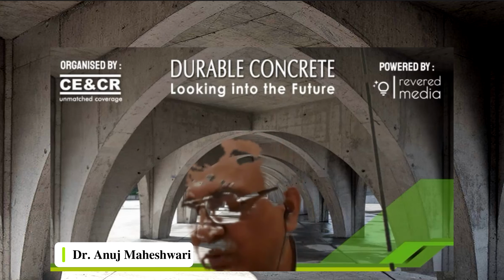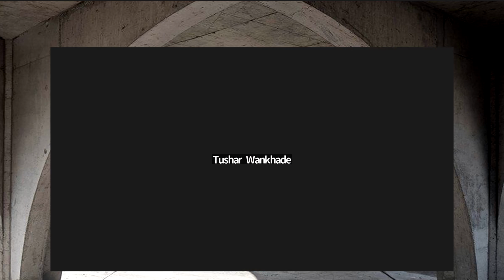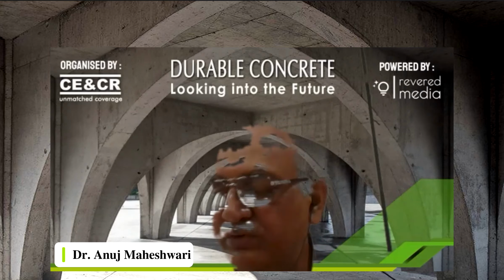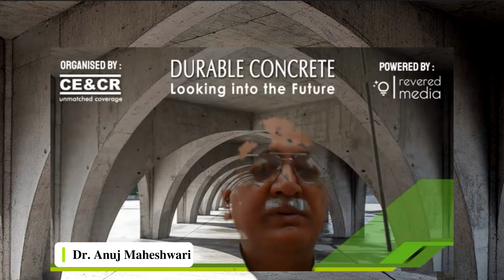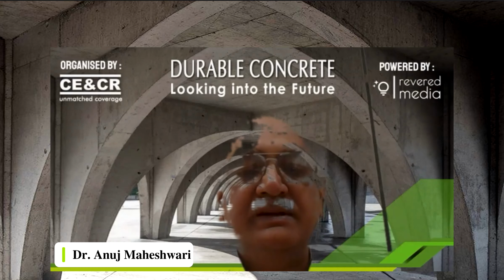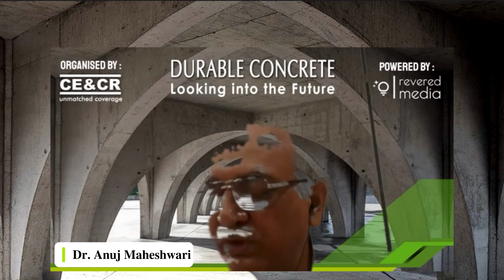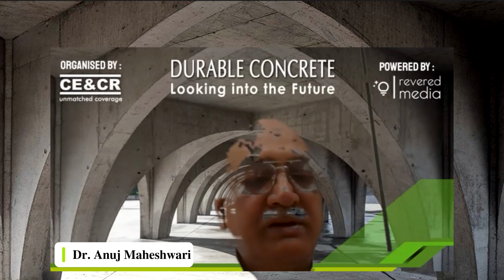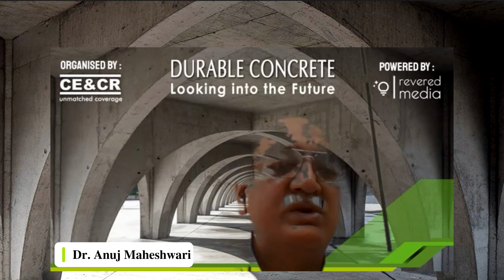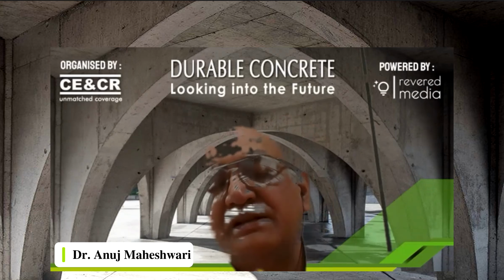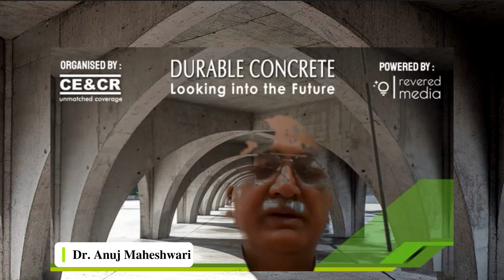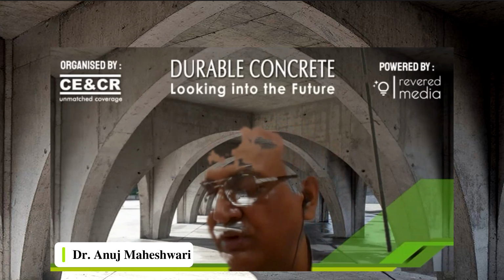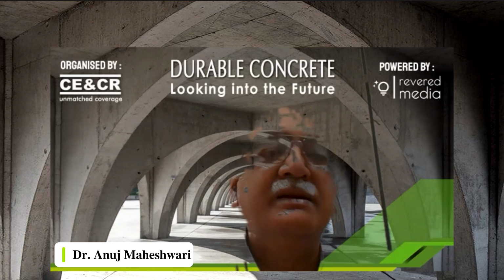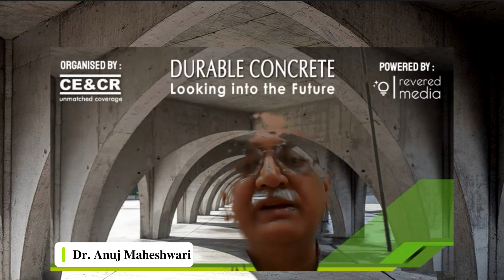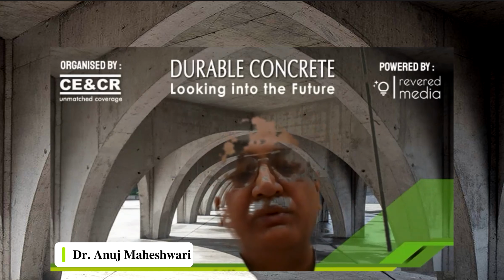Yes, sir. We are using these curing compounds extensively for our construction works. What is very important is the selection of the right curing compound. The efficiency should be more than 80%. It is true that we cannot get exactly the similar conditions to what we get under water curing. Best curing is the water curing, ponding of water. But if that condition is not available due to the site conditions, as you mentioned about high-rise buildings, you can safely go with the curing compounds, provided you identify and use the right compound.